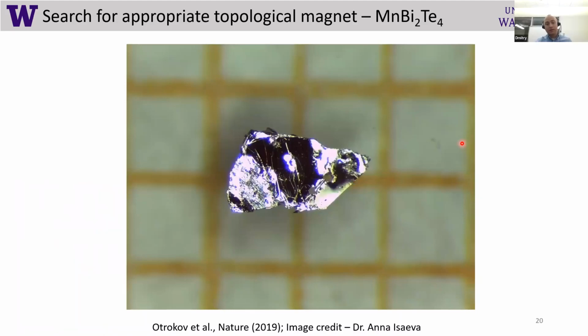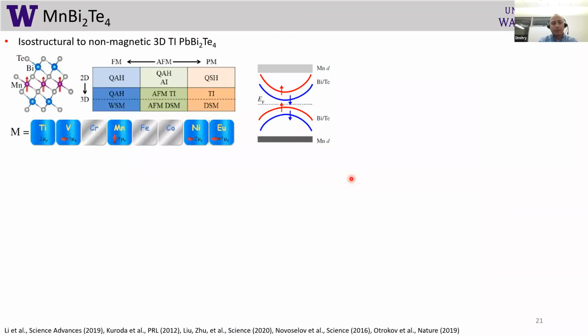As soon as there are these limitations, people have been looking for materials which could have the same physics, but also be more robust. One of the first realized topological magnets, which could be a substitute for traditional quantum anomalous Hall effect samples, was manganese bismuth telluride. This is an image from a paper by Otrokov and co-authors of a bulk crystal. So this is a bulk shiny crystal. And what do we have here in this material? First of all, it is structurally similar to other non-magnetic 3D topological insulators. For example, in this case, there is lead here, but if you substitute lead by manganese, you introduce a magnetic moment in the system.